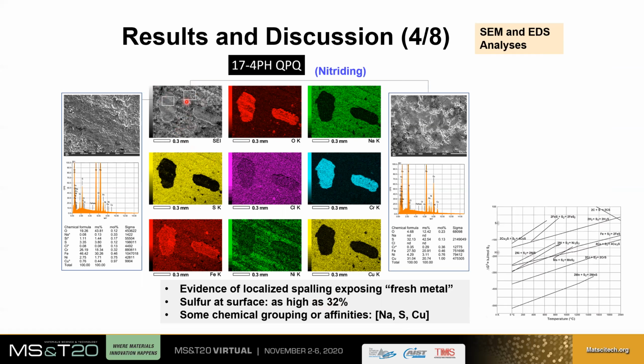and surprisingly, along with this sulfur, we do not see that much iron or nickel. What we see is copper. So remember, 17-4 PH contains 4% copper. So it turns out that actually copper appears to be the most reactive here. And there is strong evidence that this copper and this sulfur do combine and form a copper sulfide. And this copper sulfide may not be favorable in terms of obtaining a high corrosion resistance. Why do I say it's copper sulfide? Simply because this is one of the sulfides which is more thermodynamically stable among the various elements we see here.